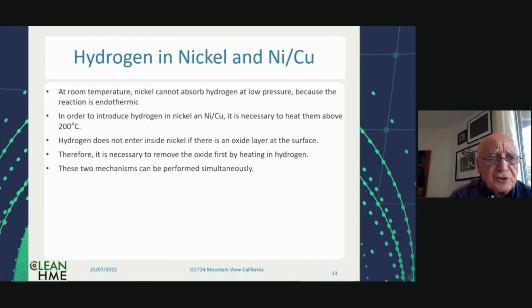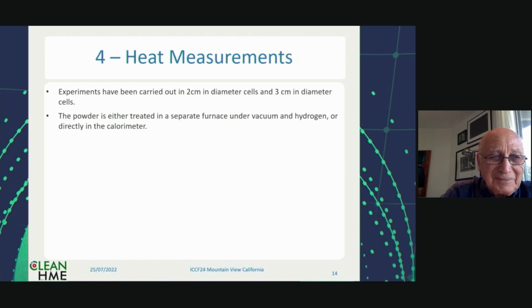Okay, at room temperature, nickel doesn't absorb hydrogen. You have to go to very high pressures. So in order to introduce hydrogen into the nickel, you have to heat it up to at least 200 degrees C. Then hydrogen will go inside the nickel. You also have to remove the oxide layer, because if there's an oxide layer, you cannot introduce the hydrogen inside the nickel. Therefore, it is necessary to remove the oxide layer first by heating in hydrogen, and then put hydrogen in it at high temperature. So these two mechanisms can be performed simultaneously. Okay, the next slide, please.